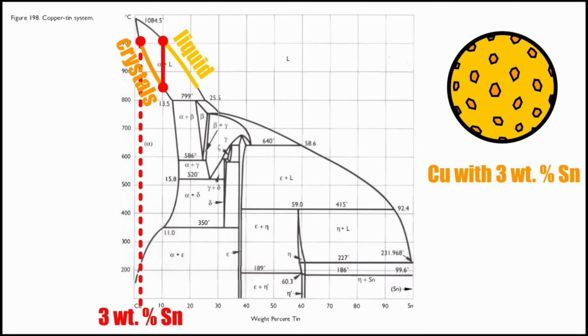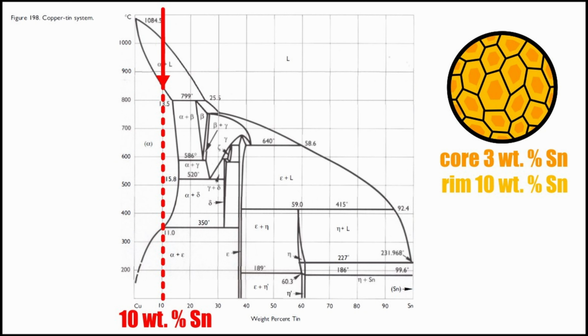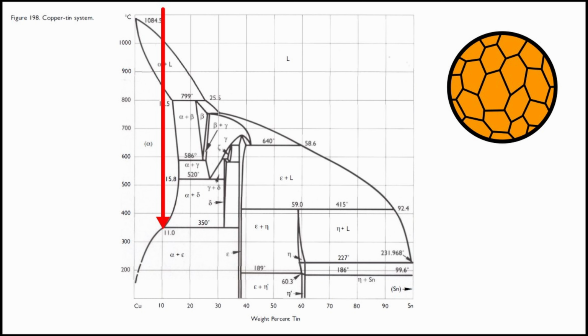How is it possible that the starting crystals contained 3% of tin and now they have 10? Why is there no coring? The answer lies in diffusion. The growing crystals are in equilibrium with the surrounding melt, exchanging atoms and removing the concentration gradient. If we cool the metal even further, we should obtain both alpha and epsilon copper phase.